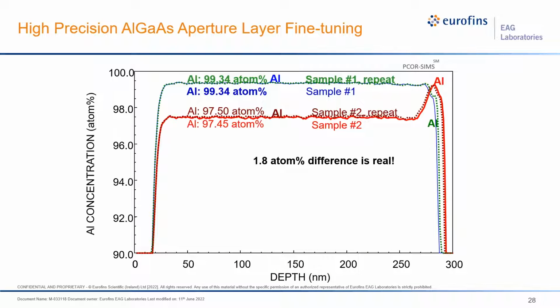With PCOR-SIMS, the aluminum composition of high aluminum content AlGaAs layers, such as those used in forming aperture layers, can be determined with a high level of precision, as shown in this figure. In these examples, the difference in aluminum content between these two samples is only 1.8% of the group 3 composition, or 0.9% of the total atoms, but the spread in measurement values of either film is much less than this. This degree of precision is crucial in perfecting these aperture layers.